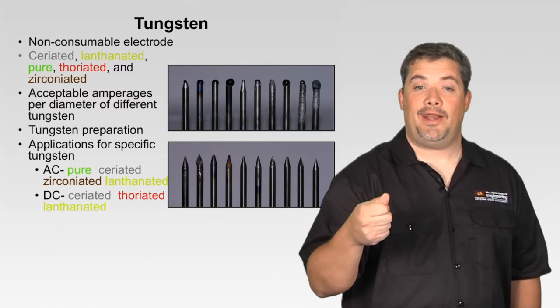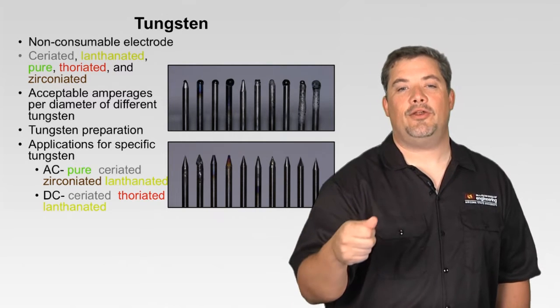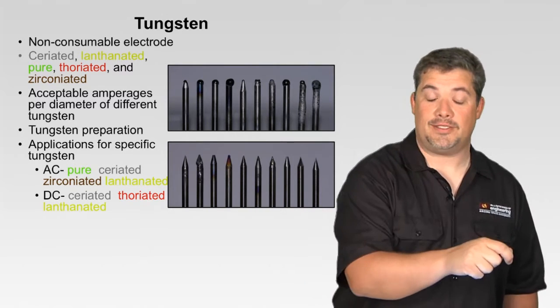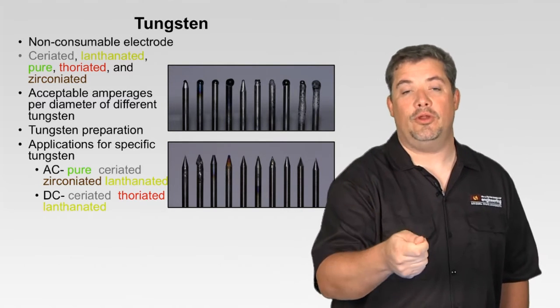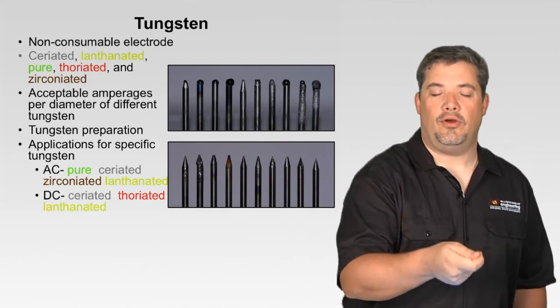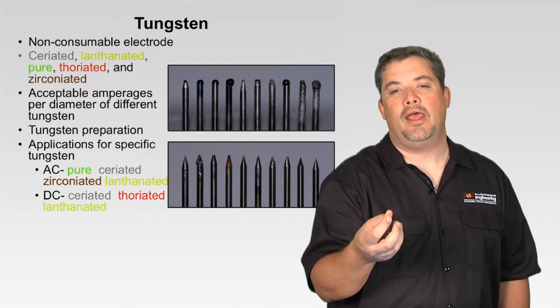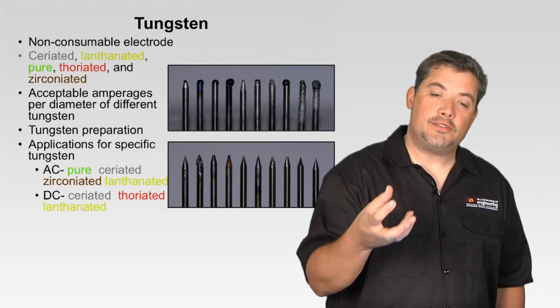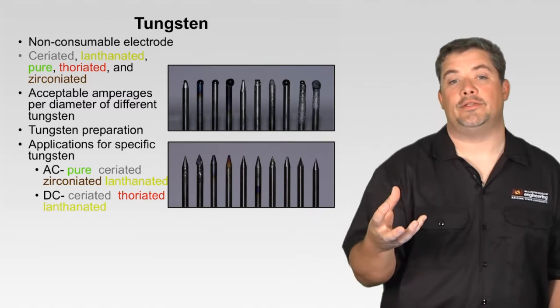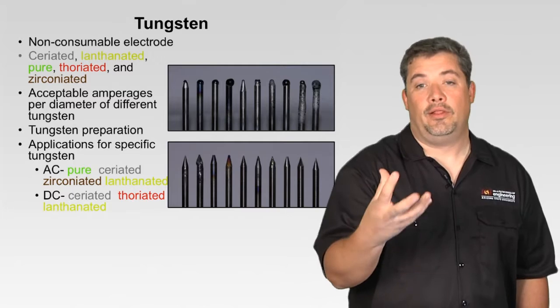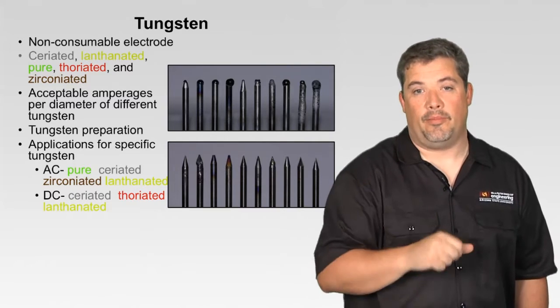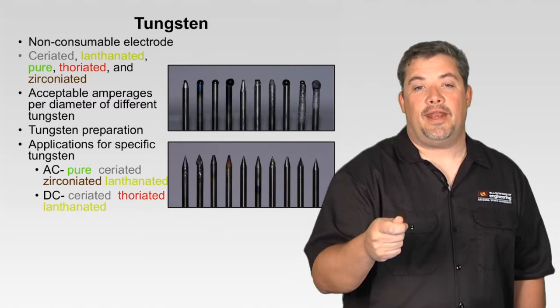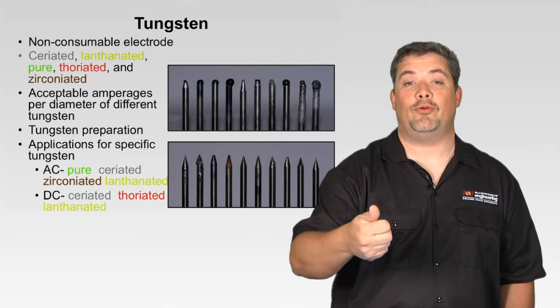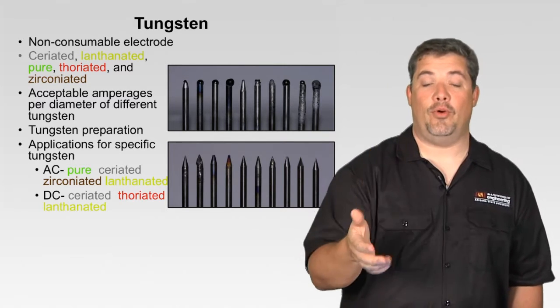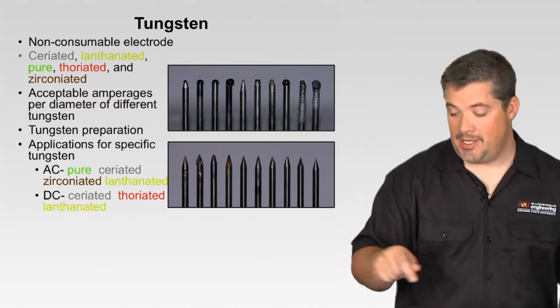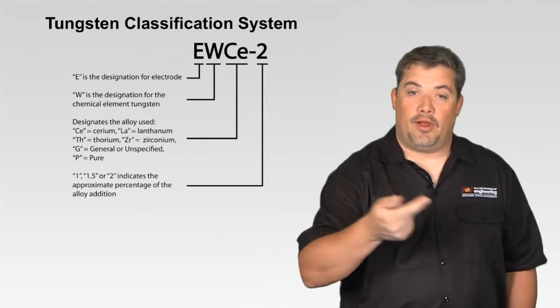But look here, ceriated works for both, lanthanated works for both. Ceriated and lanthanated are what we want to use for advanced TIG welding machines. So there's no reason anymore to use pure tungsten. That's what we used for conventional machines. Zirconiated tungsten we also used for conventional machines, and that zirconium would elevate the melting temperature of the tungsten so I could use it for heavier amperage applications where the pure may not take as much heat and therefore liquefy on the end and do what we call tungsten spitting, where the tungsten goes into the puddle. So ceriated and lanthanated work for both DC and AC, so why not keep an inventory of ceriated or lanthanated? One or the other, they both work great. Thoriated, why not thoriated on DC? Simply because it's radioactive. And we'll talk about that in just a minute.